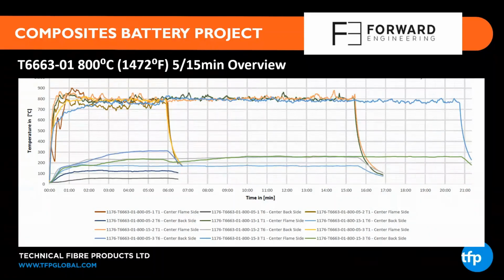And you can see from the lines towards the top of the graph, the front face of the laminate pretty quickly reaches 800 degrees centigrade or 1470 degrees Fahrenheit, and the experiments are then stopped at either 5, 15 or 20 minutes. And if you look now at the lines towards the bottom of the graph, the back face temperature is generally 550 to 650 degrees C or 1000 to 1200 degrees Fahrenheit lower than the front face temperature, showing the insulating effect of the Tecnofire, affording a high level of thermal protection to the backing laminate, which would be critical in the event of a battery thermal runaway.